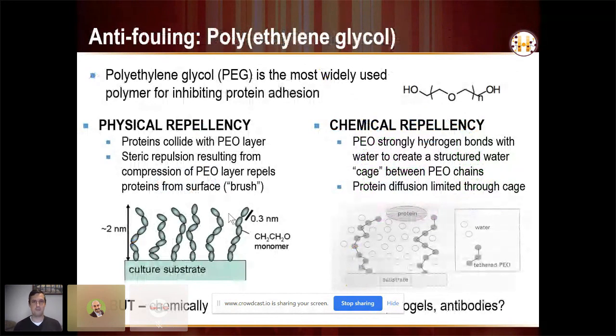glycol. And I think if you're on this call, it's very likely you're familiar with this. And this works based on two physical mechanisms. So one is sort of a brush-like physical repellency, where the high flexibility of this polymer basically sterically brushes, you almost think of it as a windshield wiper, the proteins from the surface as they come in to adhere. There's also a strong hydrogen bonding effect this polymer has because of the ethers in the polymer backbone. So we get strong hydrogen bonding with water in solution, and as a result, you get these cages of water, which make it very difficult for a protein to come in and adhere to the substrate.